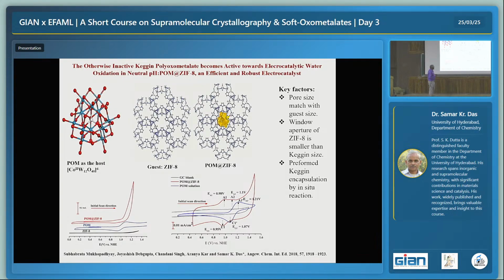Now let me tell you interesting things. As such, the Keggin gives a 2,3 couple, with no oxygen evolution. Once we put it inside, the feature completely changes. Whenever you get a huge current surge, that means oxygen bubbles come, and you can say oxygen is forming. Not only that, this compound shows continuous oxygen bubbling for 24 hours, and it works at neutral pH. I told you the Keggin polyoxometalate compounds generally decompose. In alkaline medium, definitely it will decompose. In neutral medium, it may decompose, but because we encapsulated, nothing happened. For 24 hours we gave oxygen. Again, we keep the same electrode and use it after 7 days, and it continues the same thing.